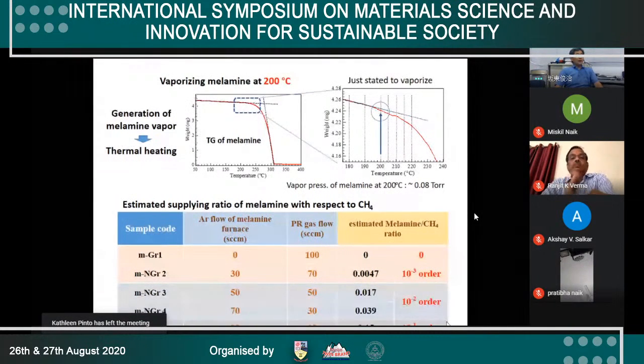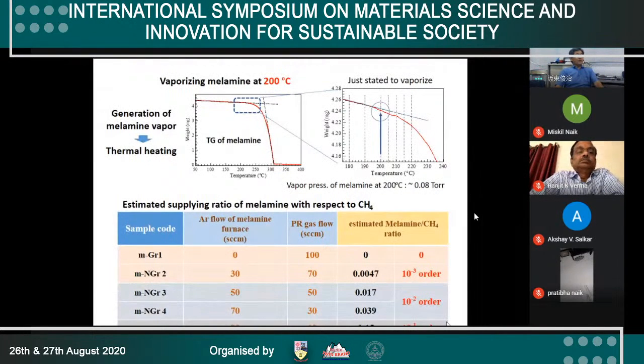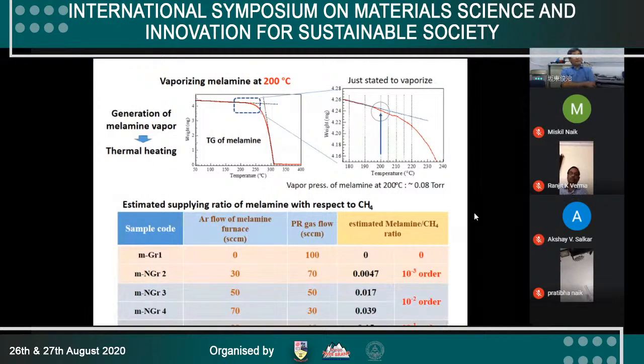The lower column is the sample code, and the top, MGR1, means no supply of melamine, and then MGR2, 3, and 4. Maybe 5 is there, but I can't see it. Anyway, with increasing melamine content, the estimated melamine to CH4 ratio, in the right-hand column, is in the order of 10 to the minus 3 to 10 to the minus 1. So the melamine ratio is increasing. Okay, next slide, please.